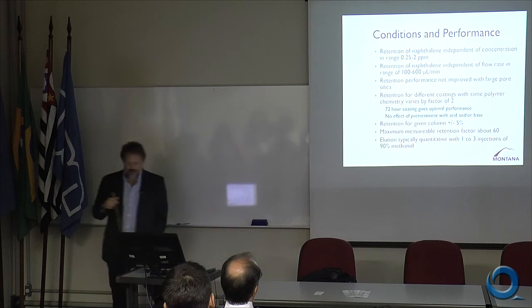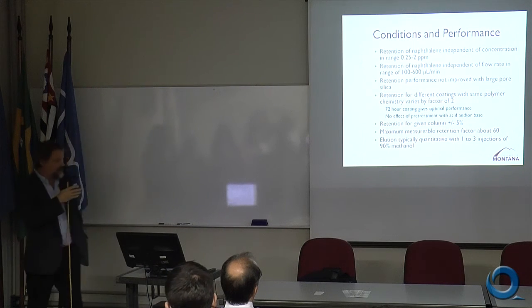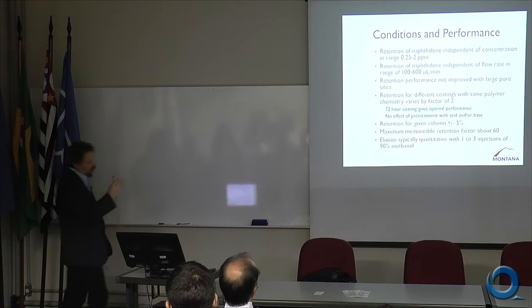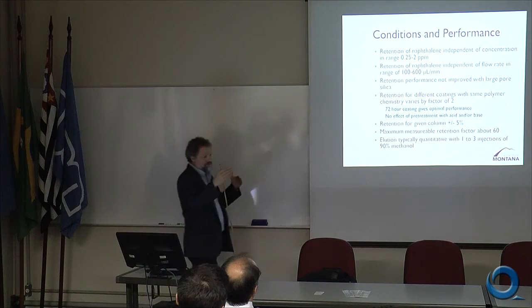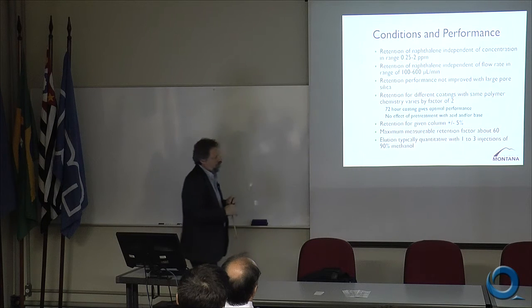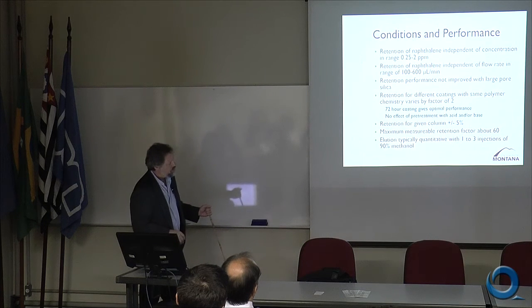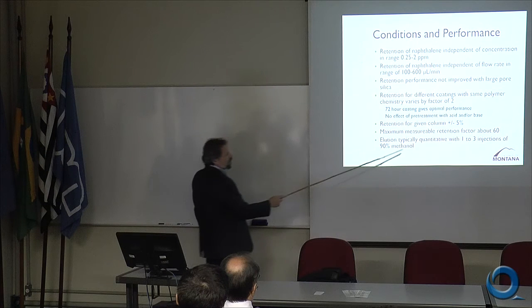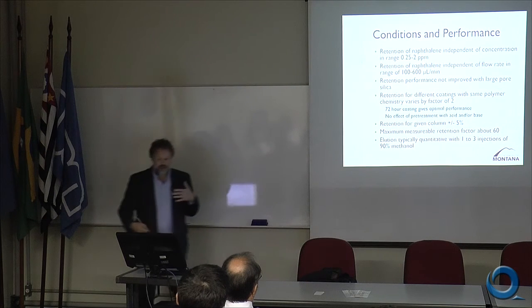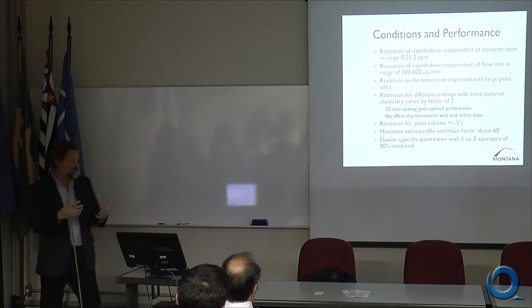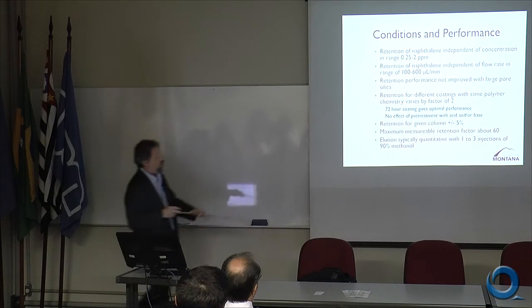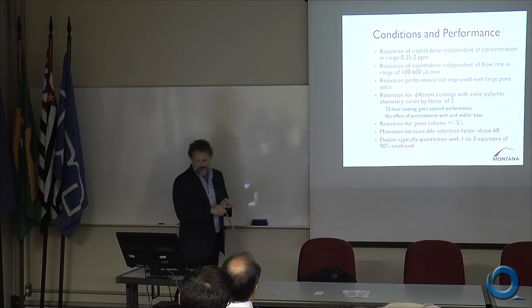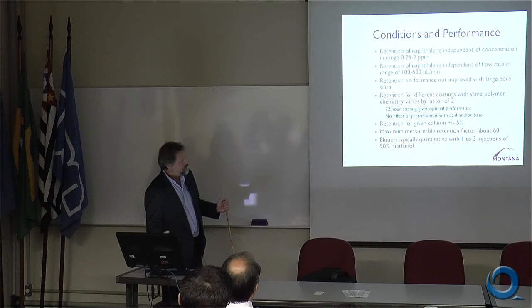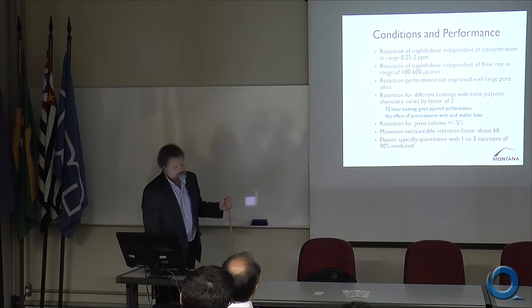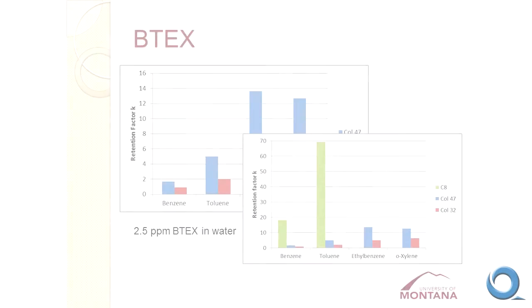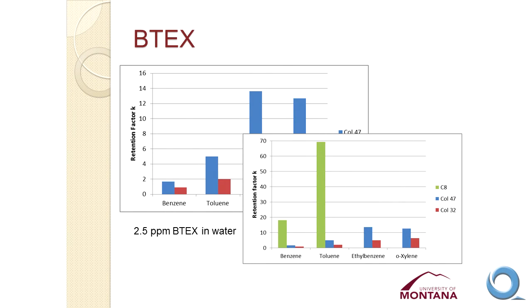Maximum measurable retention factor was about 60. Beyond that, it just takes so long to do the experiment, and the front becomes so diffuse that it's impossible to really get good results. And we were able, typically, to get all of the material back that was adsorbed to the column to be desorbed by using 1 to 3 injections of 90% methanol. So we could bring the column back to its native state by washing with the 90% methanol.